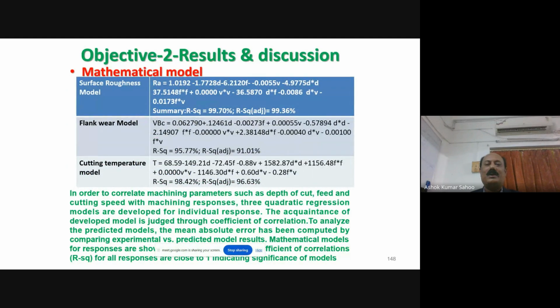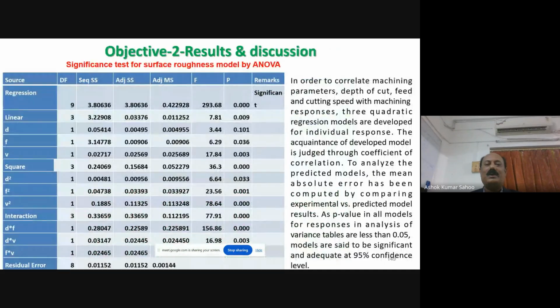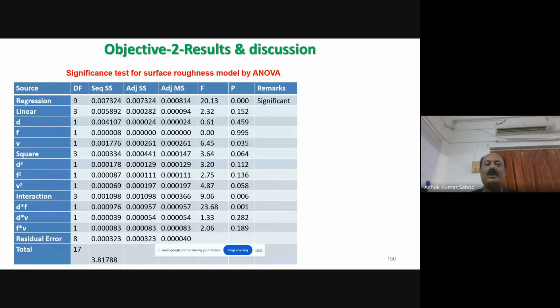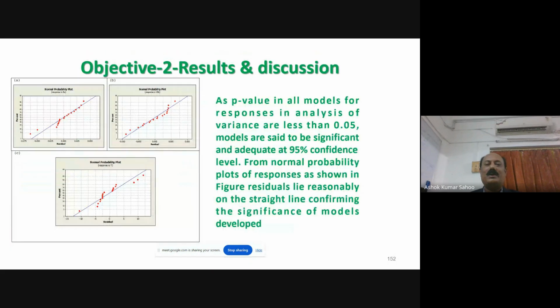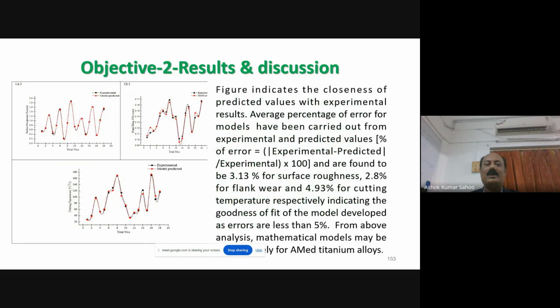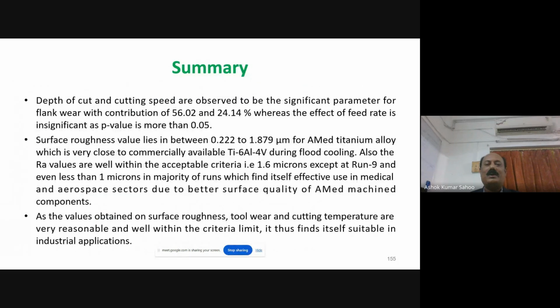Mathematical models are obtained, and the correlation coefficient and R-squared value are very close to 1, almost 95%, showing the accuracy of the model. The regression models are also significant because the p-value is less than 0.05. In the normal probability plot and the comparison between experimental and predicted values, they are also very close to each other, with errors less than 5%. So the mathematical models are found to be good for additive manufactured titanium alloy.